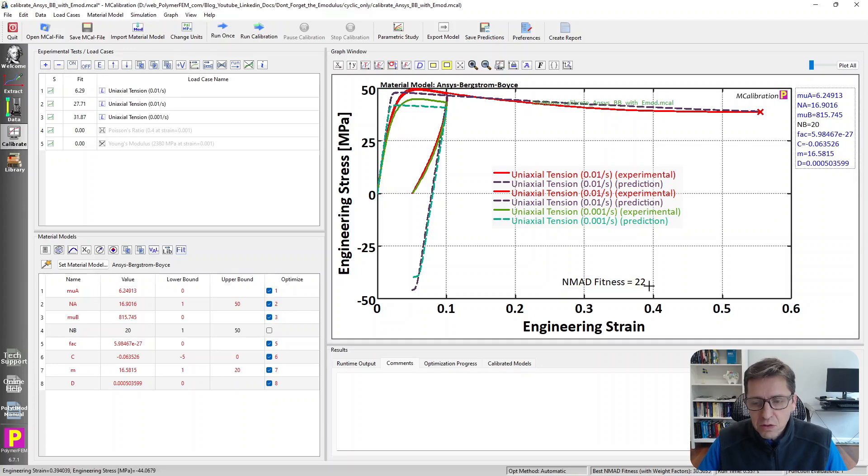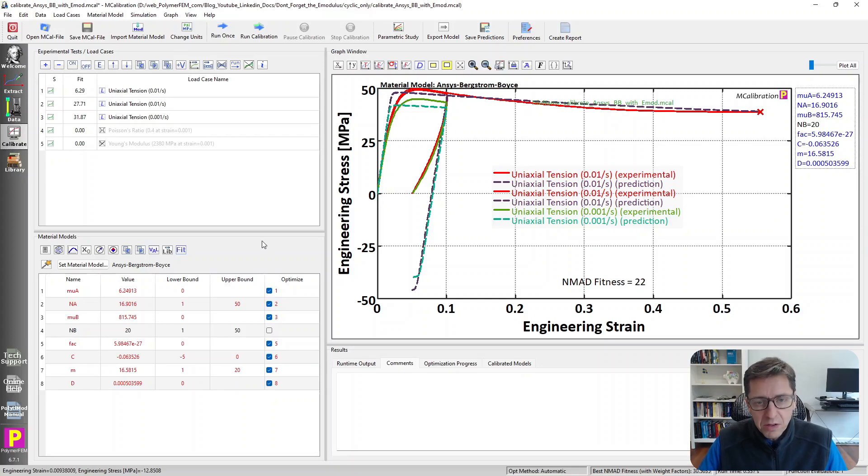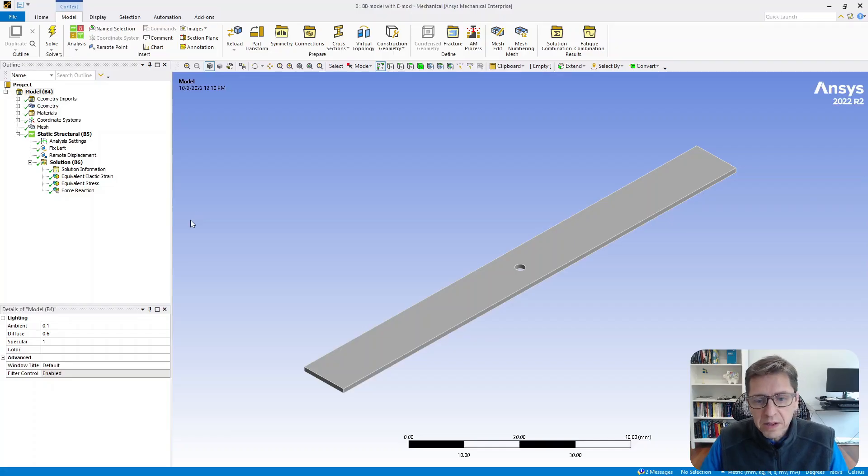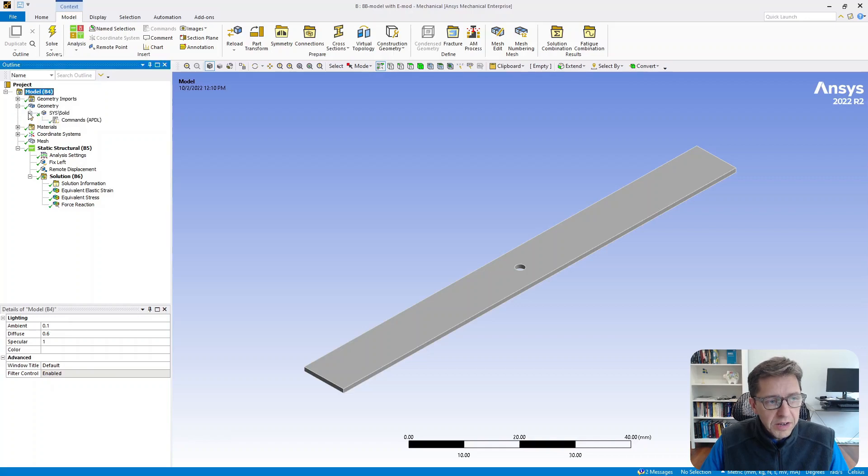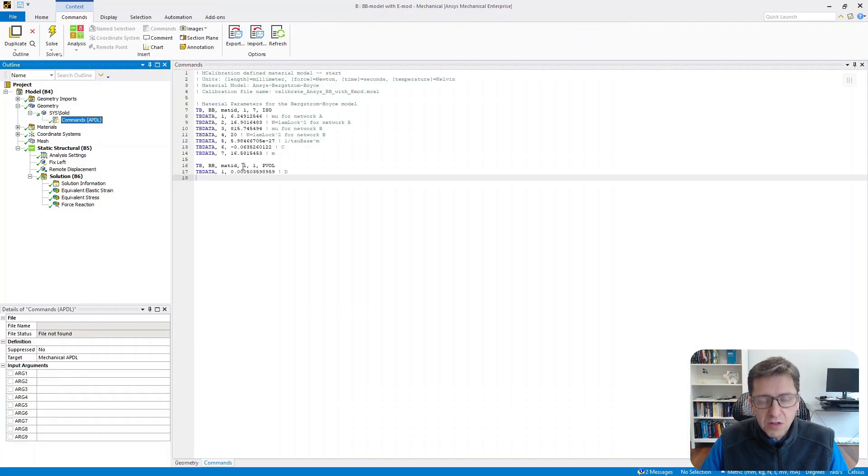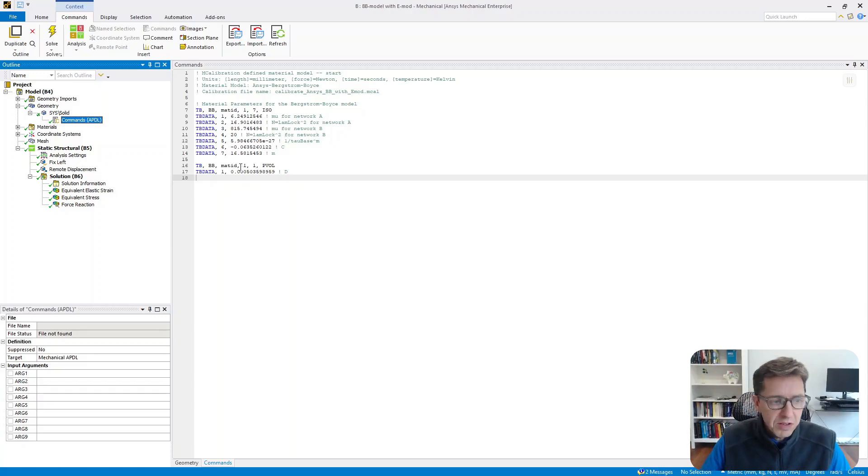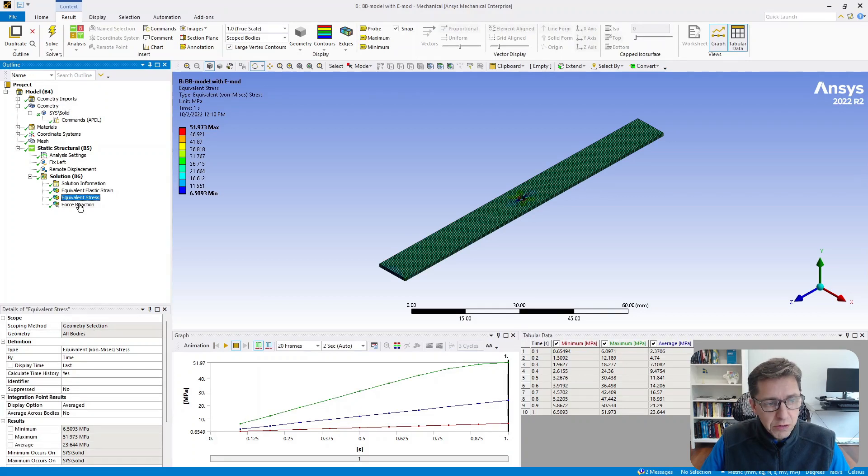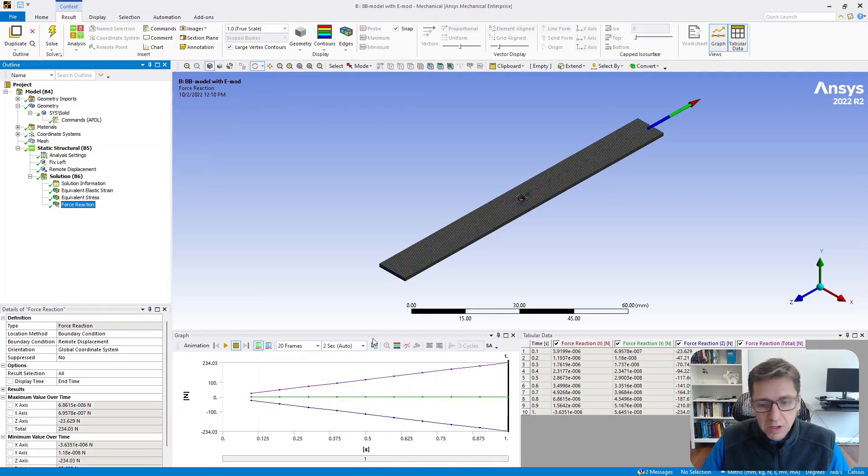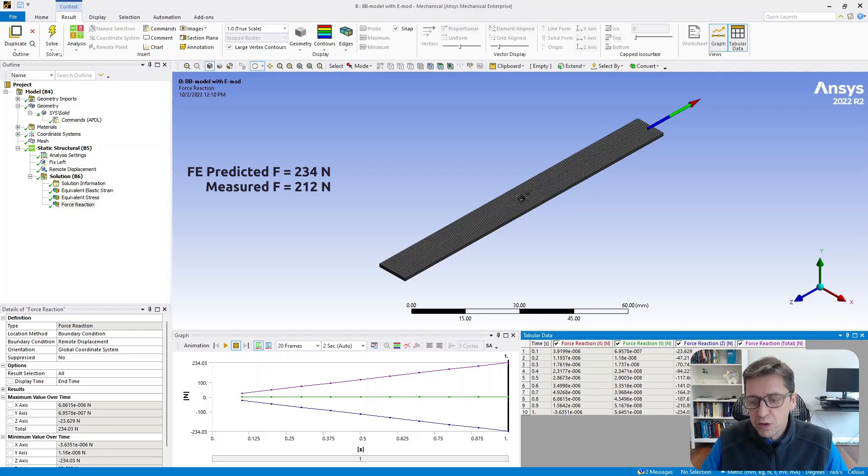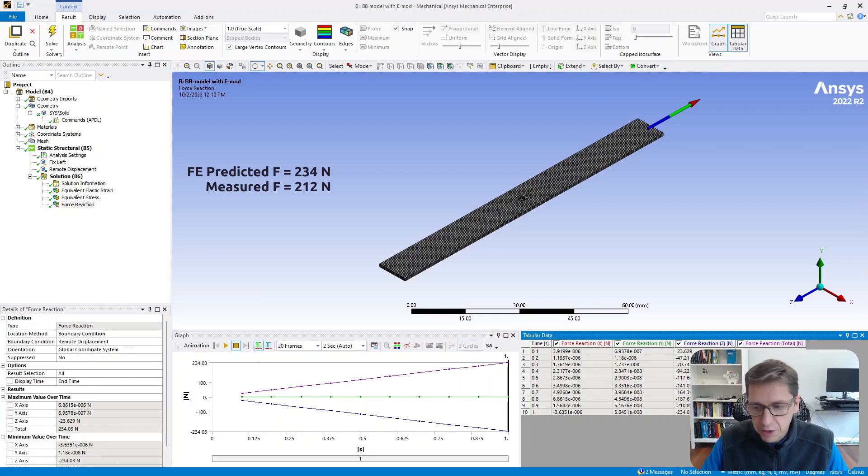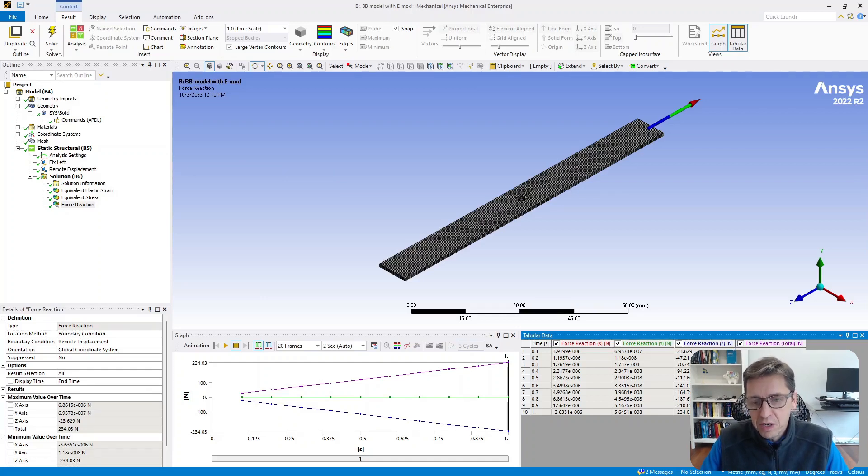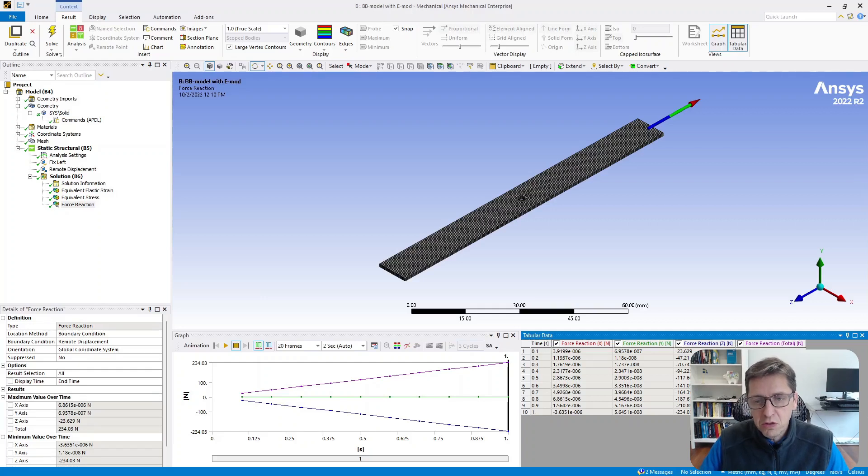And in this case, if I use this simulation here, I use this material model and I plug it into ANSYS. Let me open my ANSYS simulation for that. So here's my simulation file in ANSYS, where I use this other material model with a different initial stiffness to match the actual stiffness, even though we compromised other things. If I run this simulation, I get a slightly different response, obviously. But when I look at the actual force that's predicted here, I get 234 Newtons, and the actual value should be 212. So this is a significantly better prediction error. It's about 10%, not double half of what it should be. It's a huge improvement by doing that.